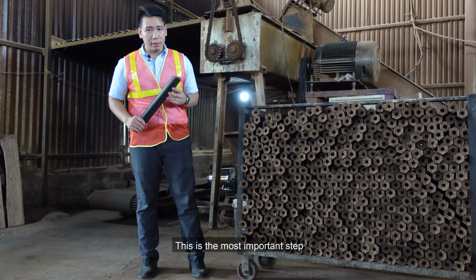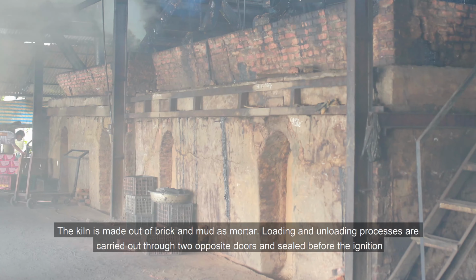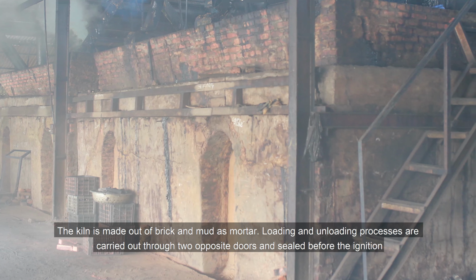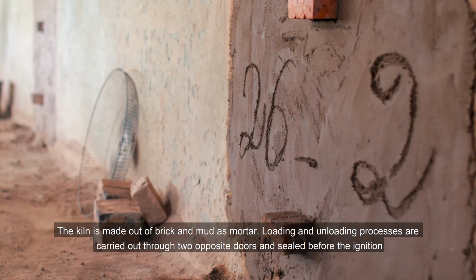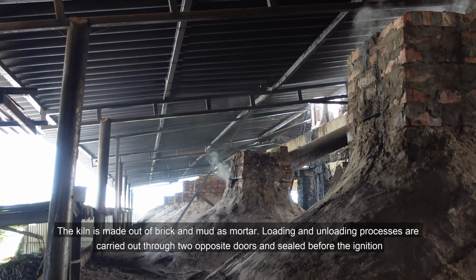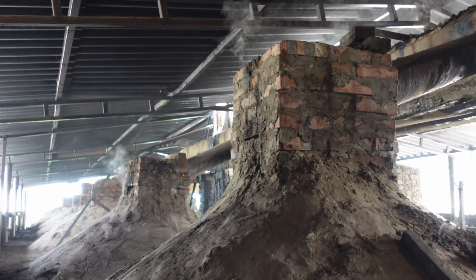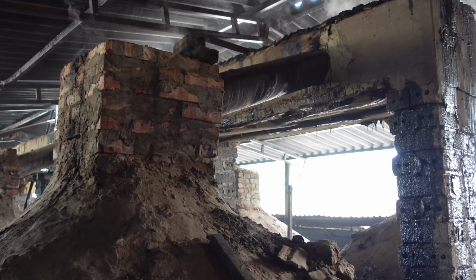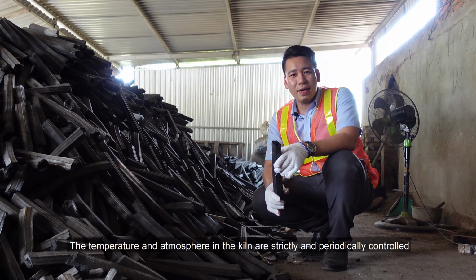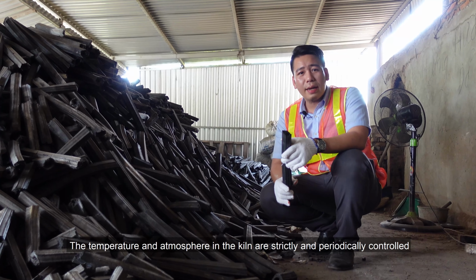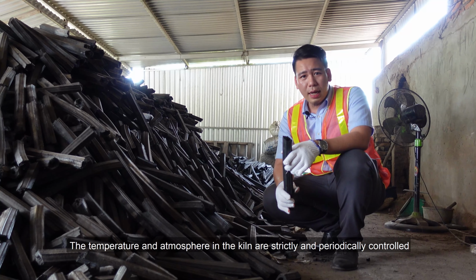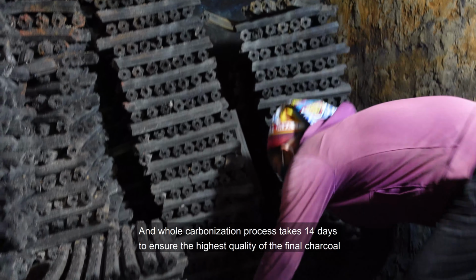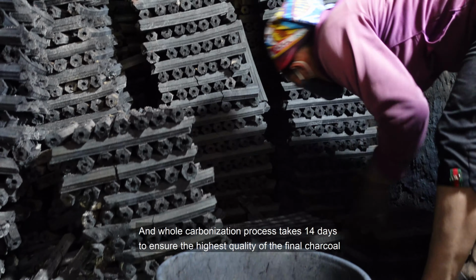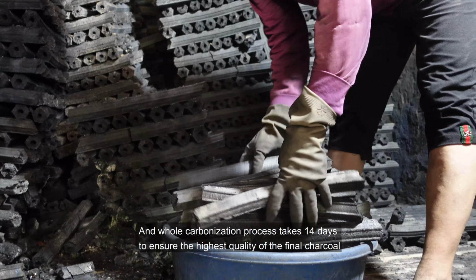This is the most important step. The kiln is made out of brick and mud as mortar. Loading and unloading processes are carried out through 2 opposite doors and sealed before the ignition. The temperature and atmosphere in the kiln are strictly and periodically controlled, and the whole carbonization process takes about 14 days to ensure the high quality of the final charcoal.